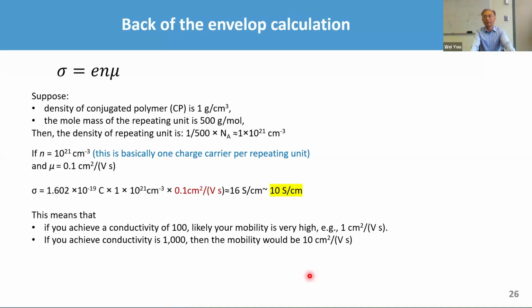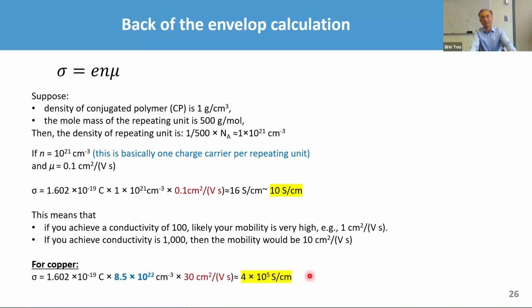So then you say, okay, what about the inorganics, copper, right? Copper is very interesting because it does not have a high mobility per se, because the mobility is about 30. Rubrene can possibly make about 30, but copper's carrier density is very high. The reason is very simple, because copper is an atom-based material. And if each atom can contribute 1 electron, you're talking about almost this level of carrier density. That is why copper has a very high conductivity, essentially like 4×10^5 Siemens per centimeter. Okay. So again, if anything you'll remember from this talk, I apologize, there are some fire trucks running by. We essentially need a high carrier density and high mobility.